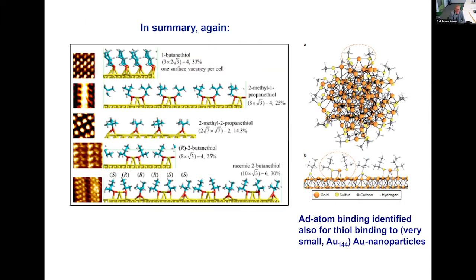Here is a summary, and we can see all the butane thiols. The singly branched butane thiol binds exclusively by the adatom binding. The tertiary butane thiol binds exclusively directly on the flat surface. If we consider the final butane thiol, that's the optically active butane thiols, the enantiomers separately bind in the same adatom bonding, but the racemic,